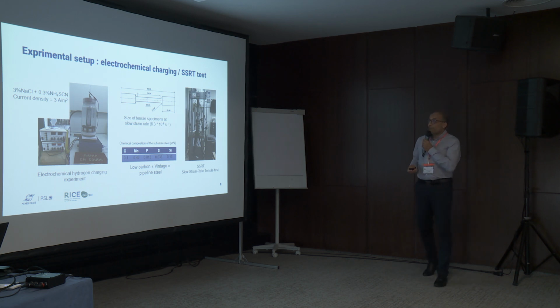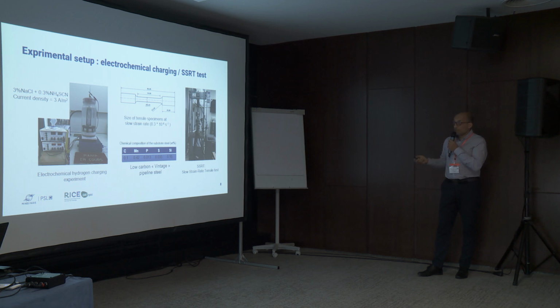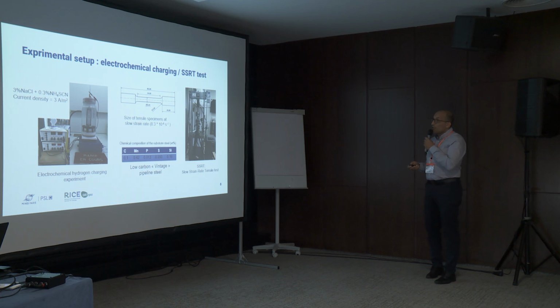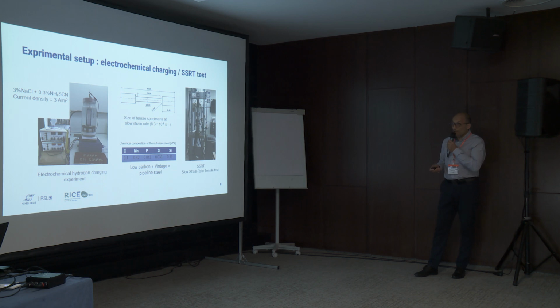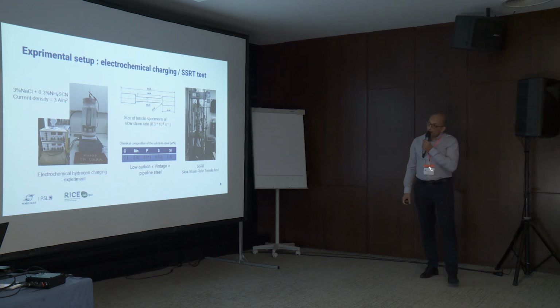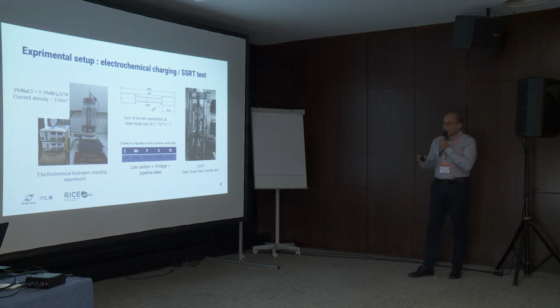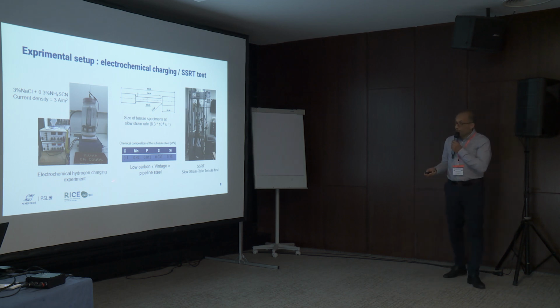So the experimental setup was done using electrocharging condition with aqueous solution, with a current density of 3 ampere per square meter. We use a low strain rate, around 10 to the minus 5 per second, and for the substrate material we use a low carbon vintage line pipe steel, X42.